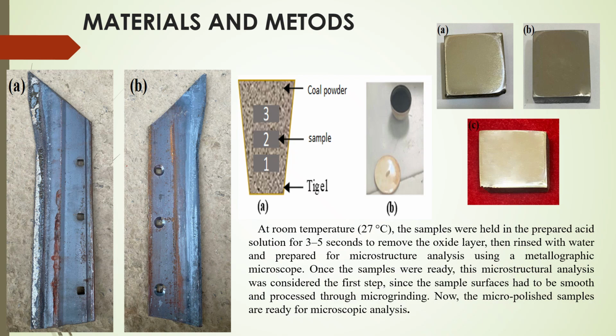Next, we prepared the samples for microstructural examination. At room temperature, they were immersed in acid solution for a few seconds to remove the oxide layer, then rinsed with water. To ensure accurate microscopic analysis, the samples were carefully microground and polished, giving us smooth surfaces suitable for metallographic observation. It allowed us to study structural changes and properties of the material after treatment.